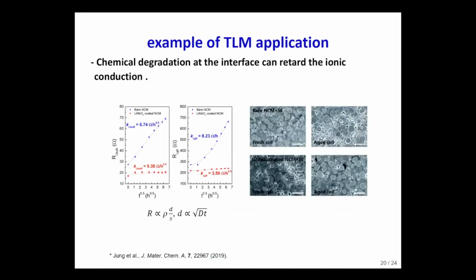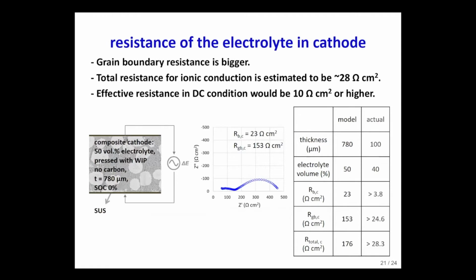And in our previous work, we demonstrated that this method could be used to study the influence of chemical degradation at the interface on the bulk and grain boundary resistance changes. So now we applied this transmission line model to determine the bulk and grain boundary resistance of our solid electrolyte inside the cathode. We prepared a composite pellet comprising 50 volume percent electrolyte and no carbon.